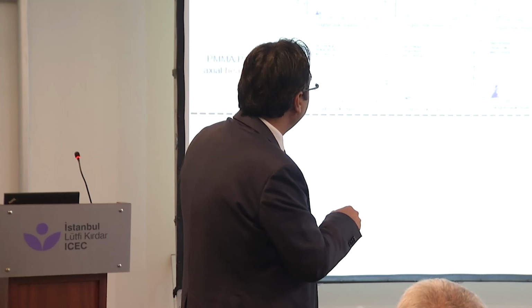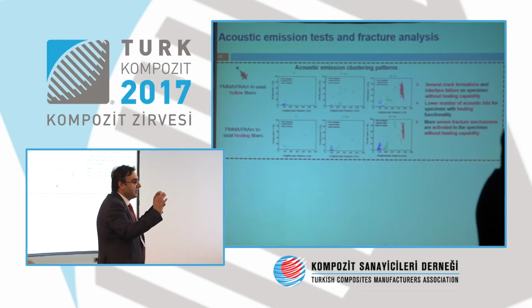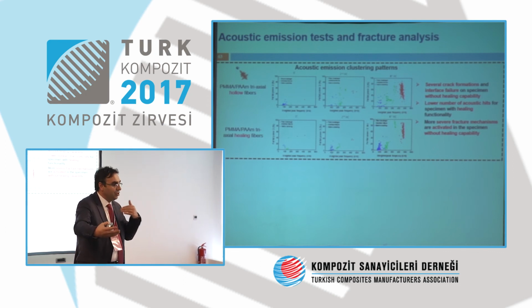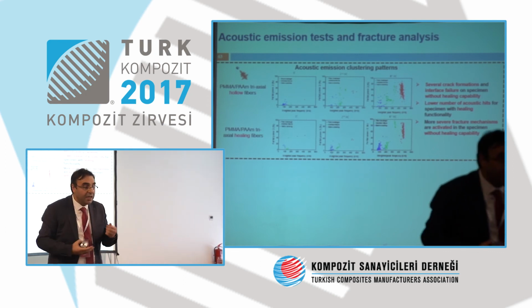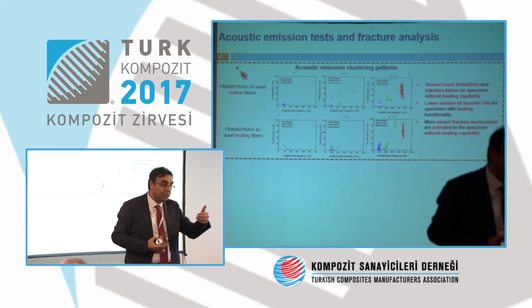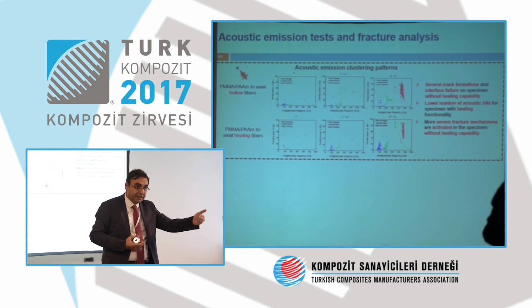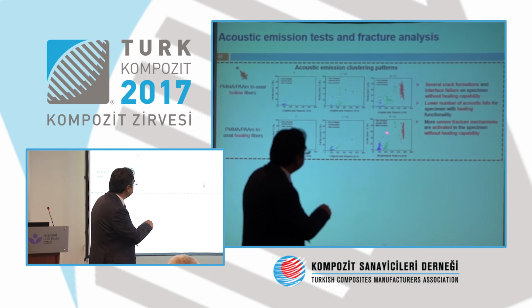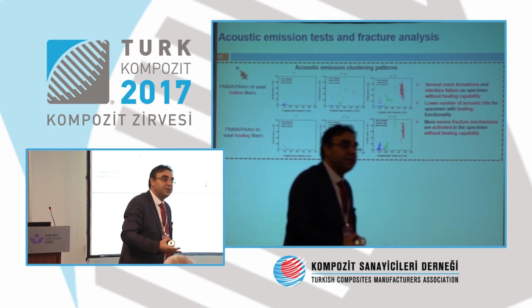Another observation I want to show you: we look at the acoustic emission data. When each crack is formed, it sends a sound wave, an elastic wave. Initially your matrix cracks, later delamination occurs through the matrix cracking, then the fiber rupture. If you repair your matrix continuously, it means you should continuously eliminate acoustic emission. This result shows that for the fourth cycle, you still have acoustic emission due to matrix cracking, but this is without repair. Look here, the matrix cracking signals are very, very low. So it indicates that you are fixing your matrix and your composite significantly.